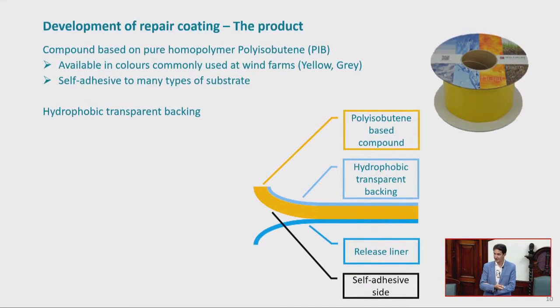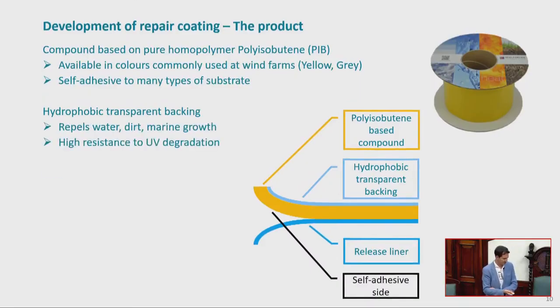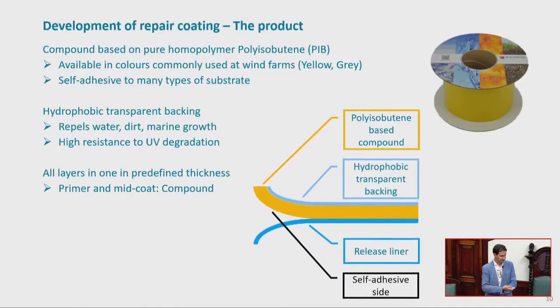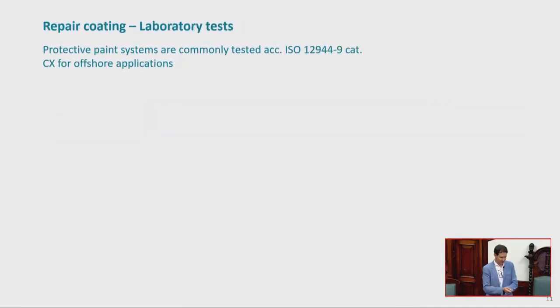So you have a layer, which is your anti-corrosive layer, and an adhesive layer in one. And you have a backing that comes on top, which gives you UV resistance. And it's an ETFE, so it also gives you some self-cleaning properties and so on, so dust and rust won't accumulate and it won't chalk over time. Actually, recently we had a comment if it can chalk over time because the rest of the coating is chalking, so then you can clearly see every patch after a few years in service. But no, we'll keep it as good as we do. So that's more or less how it works.